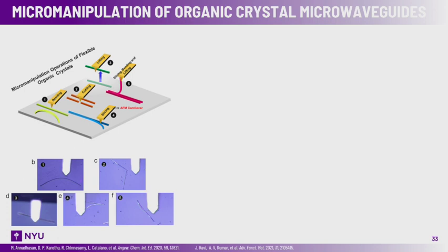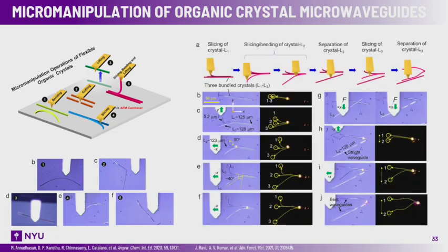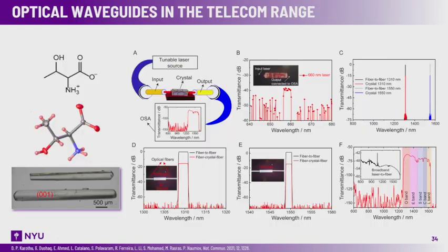Now the problem is, how do we scale this all down? And our way to do this, since we have the problem with manipulating crystals on a small scale, is to use AFM. So we use an AFM tip to cut, to slice, to bend crystals, and to manipulate them in all ways. Using this technique, I have other examples to show you, but this is just one typical example. We can assemble them in optical circuits on a micro scale and then use them as microscopic optical transducers.